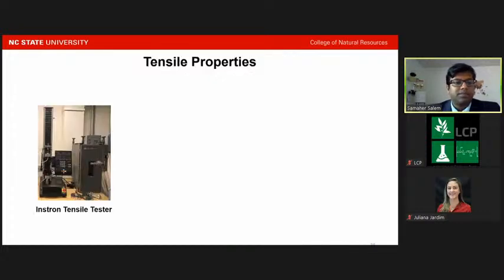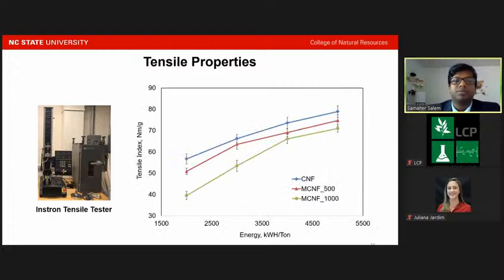For tensile properties, we used an Instron tensile tester, the standard method to measure the tensile properties, and we could find that the tensile properties were higher for the unmodified nanofibrils. However, with the extent of modification, the tensile properties decrease. This is understandable because with the attachment of the acetyl group, the closeness of the nanofibrils to each other and the hydrogen bonding decrease, since the acetyl group replaces most of the hydroxyl groups of the sample. Thus the tensile index decreases, because the hydrogen bond is responsible for the higher tensile index of the nanofibrils in the system.